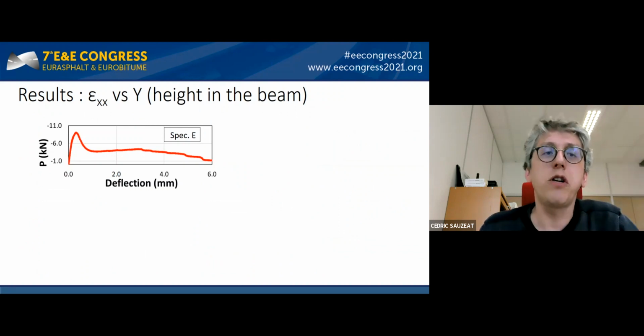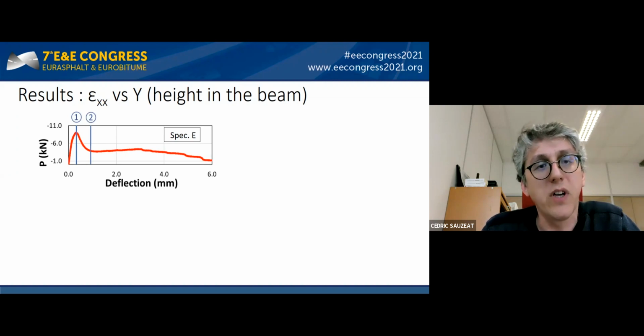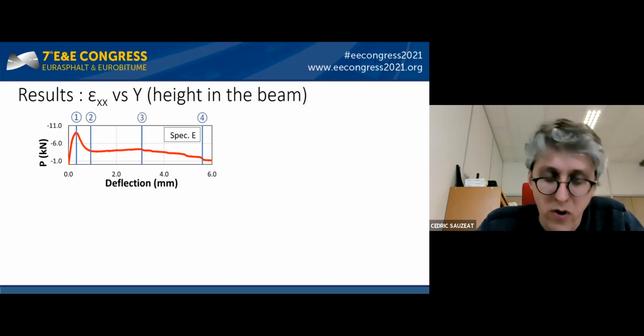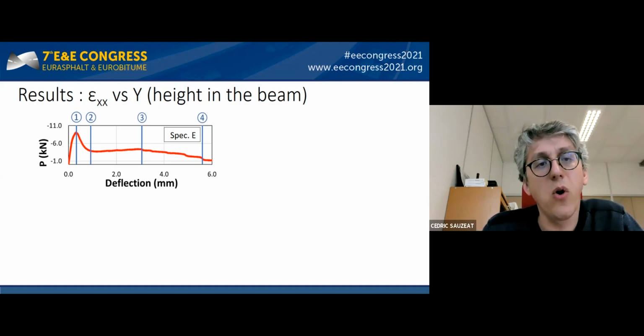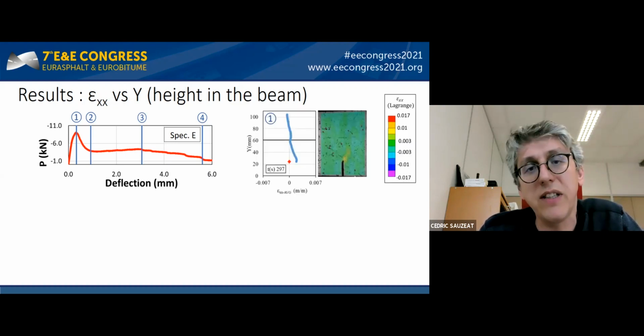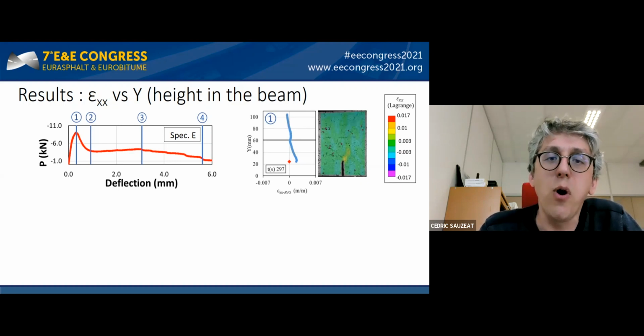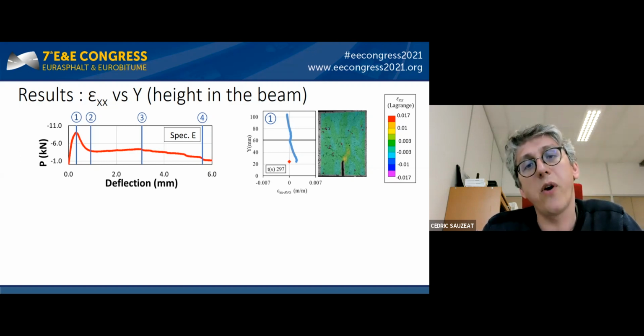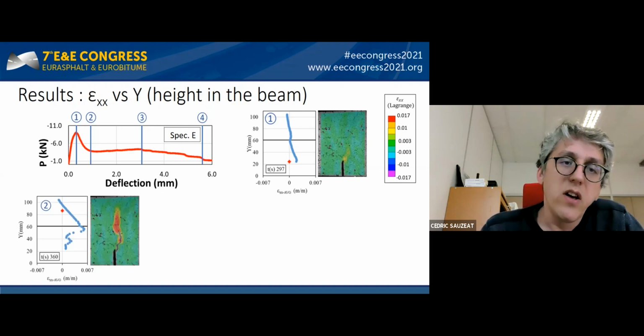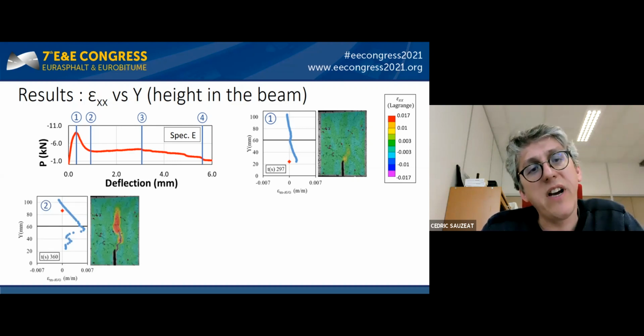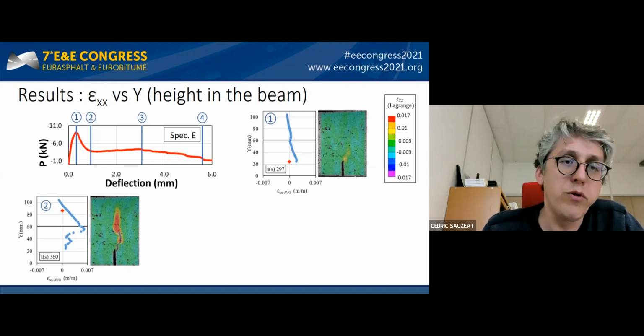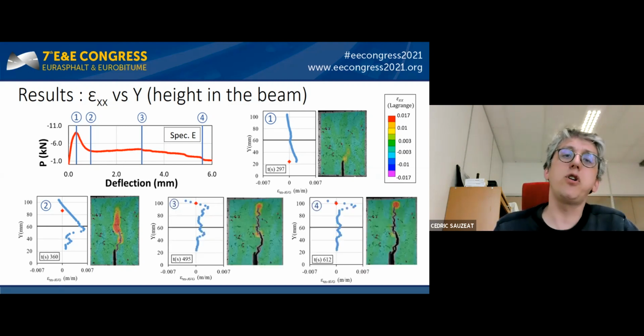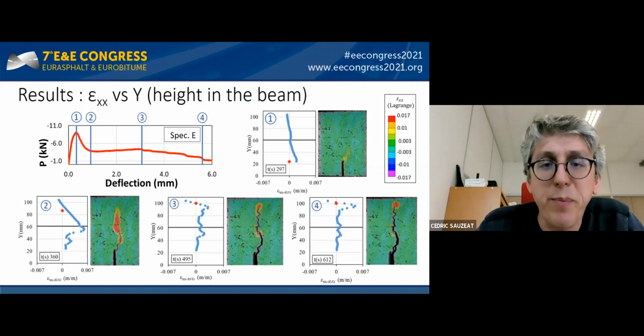The last result, the evolution of the strain in function of the height of the beam. So we will analyze 4 points along the test. The point one is at the peak. You can see that the crack didn't propagate yet, and you have an almost classical linear evolution in function of the height of the specimen. Here, you have the crack that has propagated and the linear evolution is only close to the crack. And the linear evolution reduces more and more when the crack propagates.